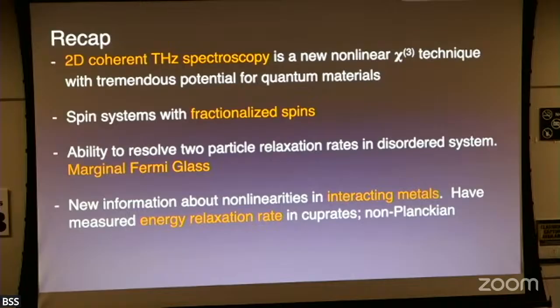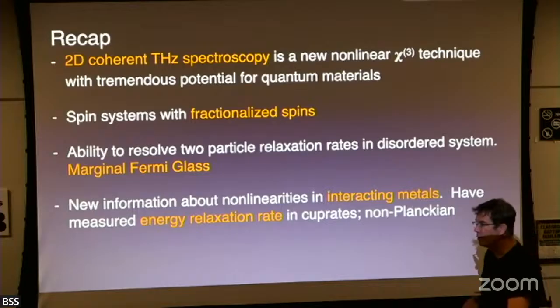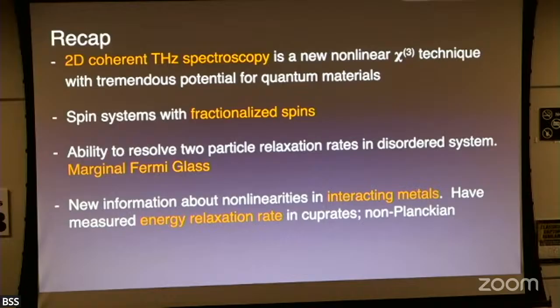You start in the superconducting state, warm up, the nonlinearities die like an order parameter, and they're basically 0 in the normal state. As you disorder it, and we worked on a bunch of samples, as we get close to the metal insulator transition, and you get down to kFl at about 2 or something thereabouts, the nonlinearities kick up, and by the time you get to kFl of 1 or a half, at the metal insulator transition, you get nonlinearities in the normal state. Clean niobium nitride has a Tc of about 14 Kelvin, and these nonlinearities persist all the way up to like 30 Kelvin. I don't know what to make of that. We speculate about all kinds of things that you can imagine in our paper.